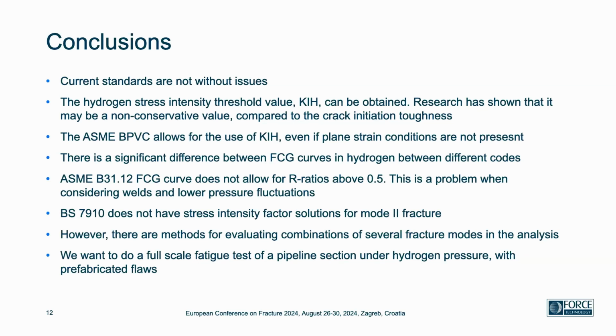Conclusions. So first of all, the current standards are not without issues. I know that a lot of standards within the hydrogen industry are in development, so I am still waiting to see how they apply fracture mechanics in the new standards that are coming. The hydrogen stress intensity threshold value K1H can be obtained, but research has shown that it may be a non-conservative value compared to the crack initiation toughness. And as I mentioned earlier, the boiler and pressure vessel code allows for the K1H even if plane strain conditions are not present.